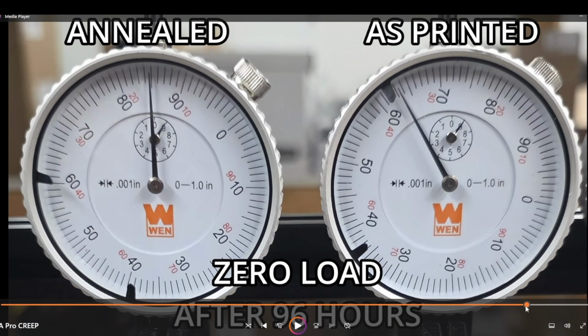And then the next day when I took the weights off, I let it sit for an hour, and this is where it retracted back to. And basically both pieces retracted back 15 thousandths from where they peaked out at during this test. So the annealed came back to 15 thousandths and the raw 36 thousandths.